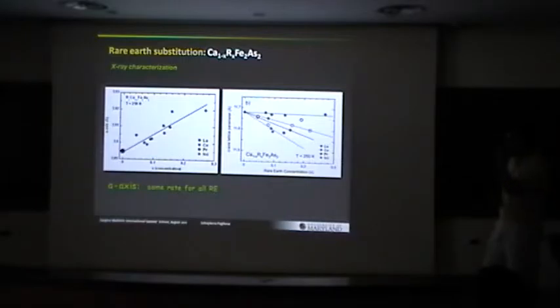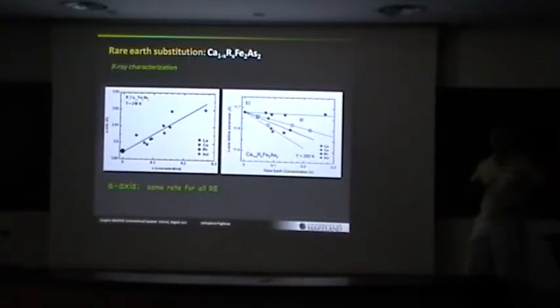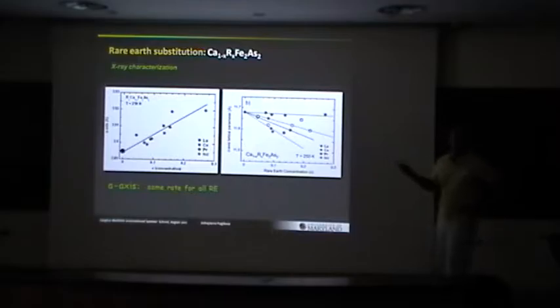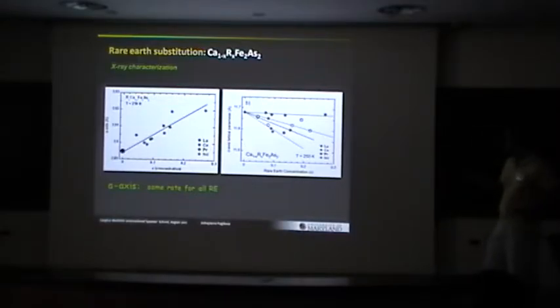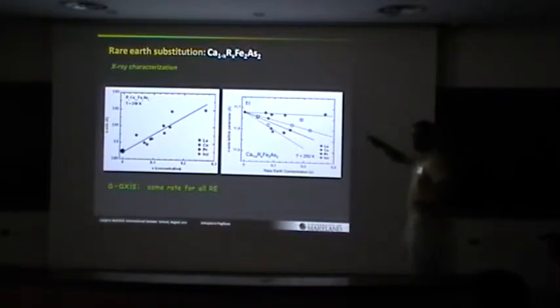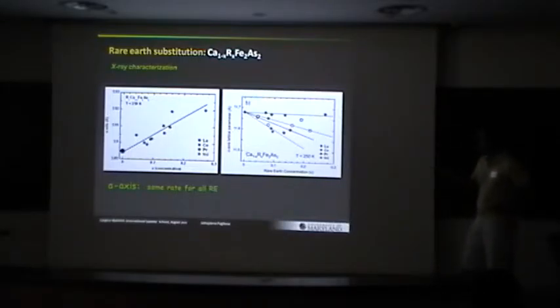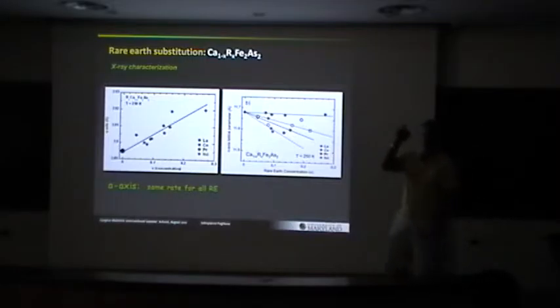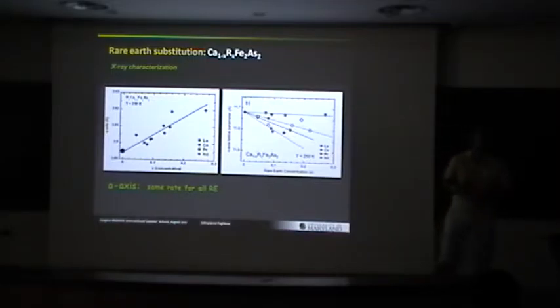Okay, and then if we characterize the unit cell parameters as a function of rare earth concentration: this is the a-axis. There's some scatter here, but more or less the a-axis increases with all the rare earths we put in. It doesn't matter about their size. The c-axis, however, is very strongly dependent on the size. So lanthanum very minimally suppresses the c-axis. It's almost constant. Whereas the other extreme, neodymium, strongly suppresses the c-axis. So this is what we want. We want to put in small rare earths and cause this collapse to occur at ambient pressure.